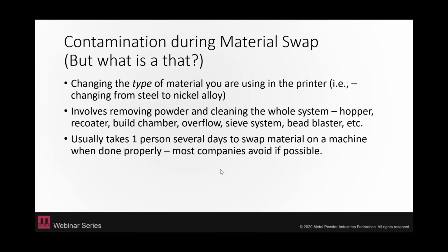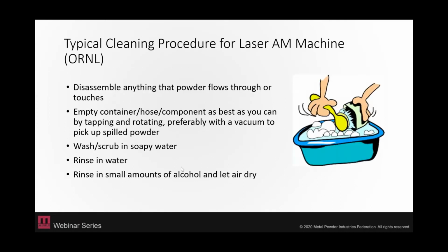And this is why most companies avoid this if they can. They will buy a machine for a specific material and never change that material because it is such an involved process. So just typical cleaning procedure is you really just have to disassemble anything that the powder flows through or touches. You have to empty those components as best you can, tapping and rotating, vacuum them out. And then we wash and scrub with soapy water, we rinse, and then we use small amounts of alcohol to let it dry. So that's just our general procedure.